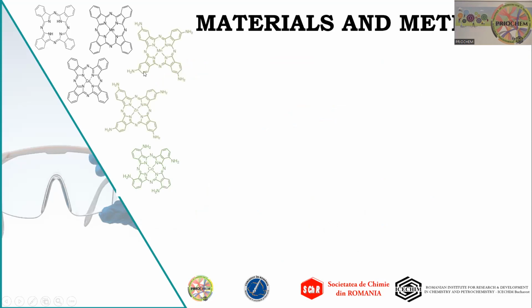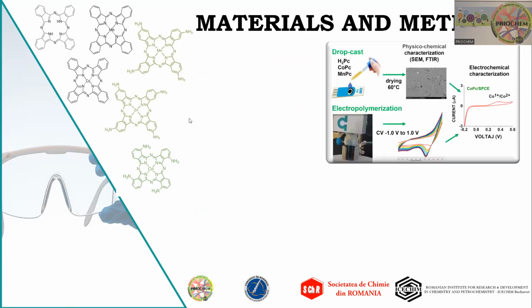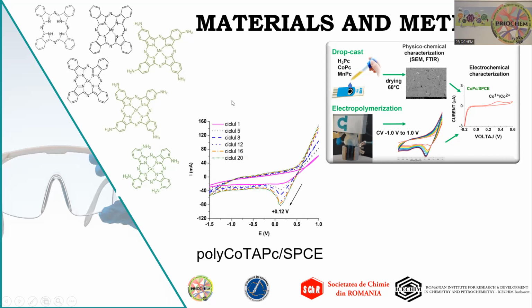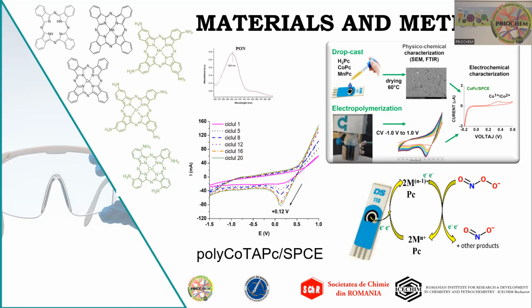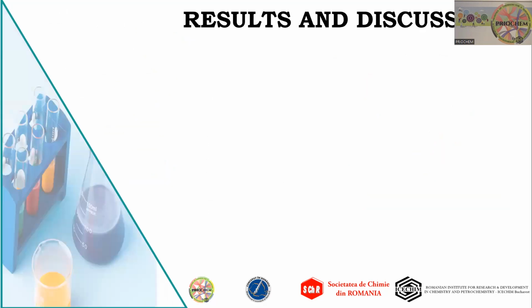I'm using mainly cobalt phthalocyanine and other metal center phthalocyanines to modify the screen-printed carbon electrodes by electropolymerization in different ranges, and by drop casting. I will characterize these prepared electrodes by different physical chemical and electrochemical characterization. Here, for example, in the middle, we have electropolymerized polycobalt tetraamino phthalocyanine screen-printed carbon electrodes with a different number of cycles. That can lead to the mechanism presented on the down right slide.